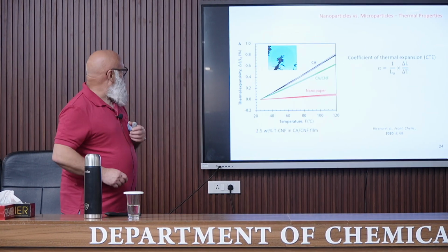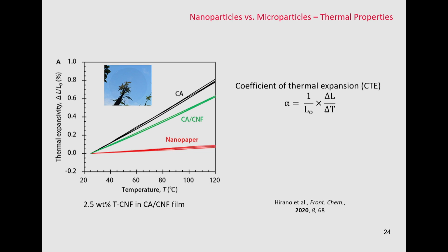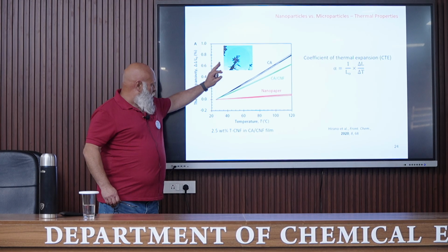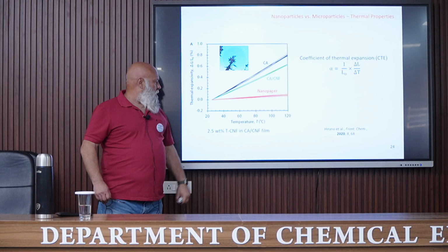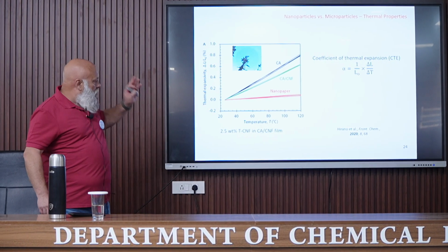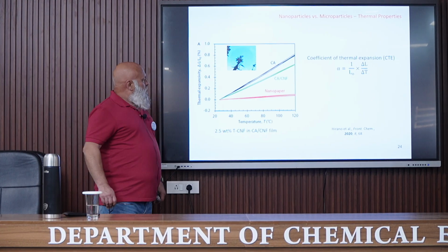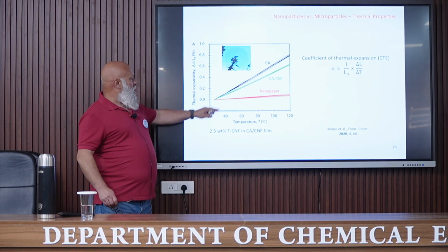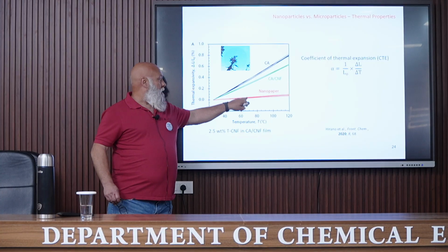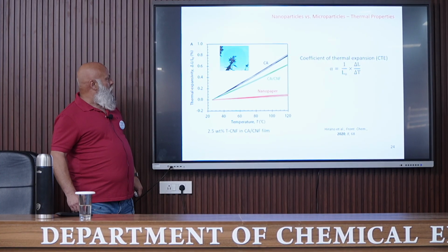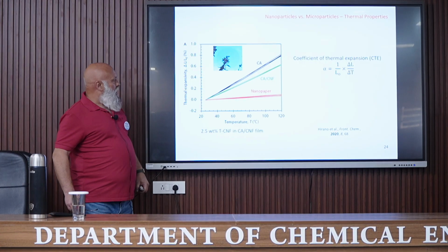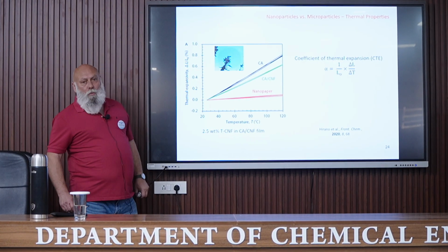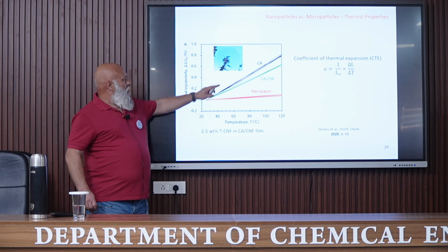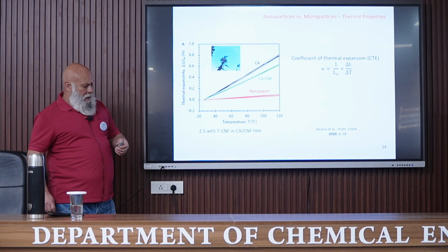I have one example, which is here. This is the thermal expansivity as a function of temperature for cellulose acetate, which was the matrix, and for a nanopaper. I think it was TEMPO-oxidized cellulose nanofibril, but I don't remember the origin of cellulose, but it's not very important. So the thermal expansion coefficient that corresponds to the slope of the curve is very low. It's much higher for cellulose acetate, and for the composite containing 2.5% cellulose nanofibril, you can see that we have a reduction in the thermal expansion coefficient.